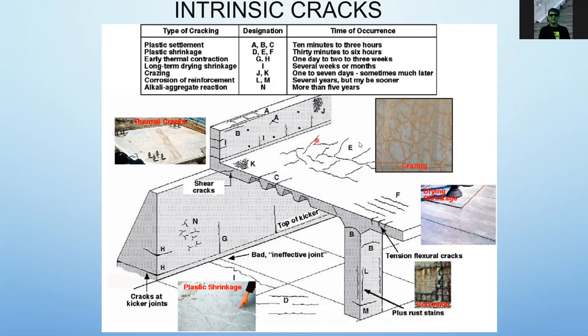As shown in this figure, letter E shows cracks on a slab — specifically plastic shrinkage cracking in a floor slab, which can appear within 30 minutes to 6 hours. We should prevent these cracks to stop water from penetrating the slab, parapet wall, retaining wall, or columns. Water penetrating columns will cause the reinforcement to rust, and when reinforcement rusts, it will expand and affect the structural stability of the column or building.